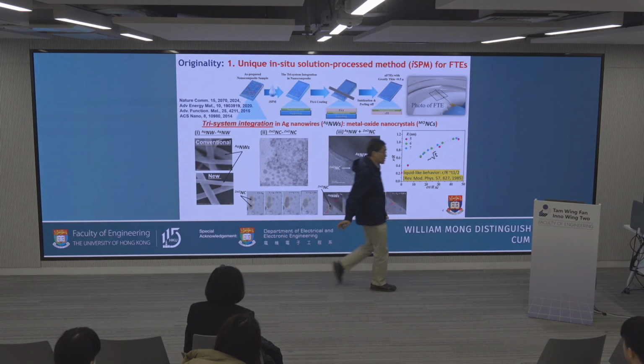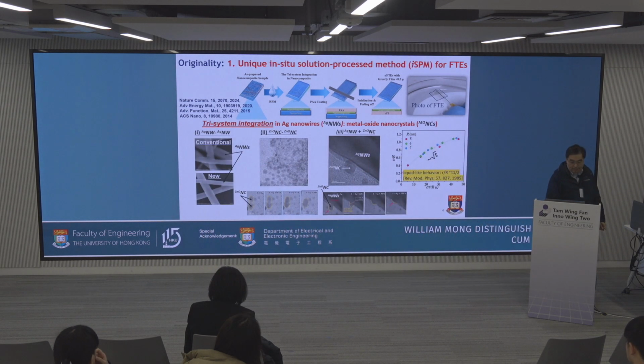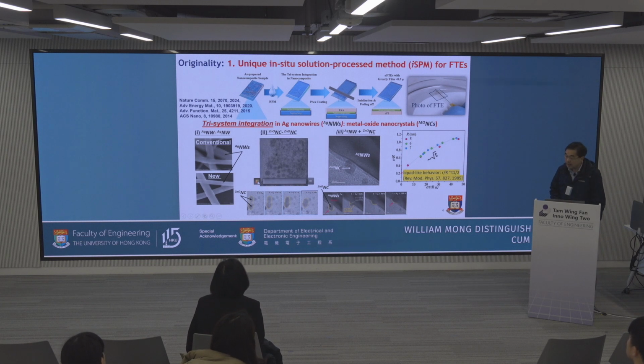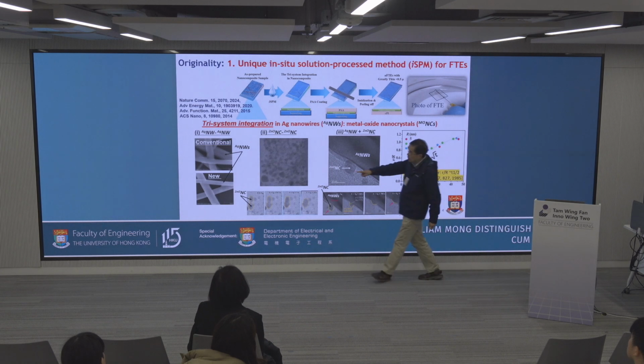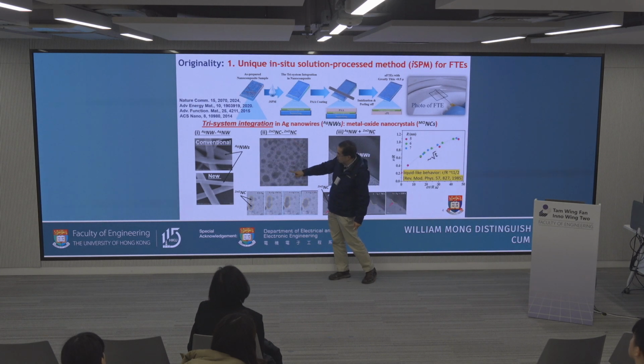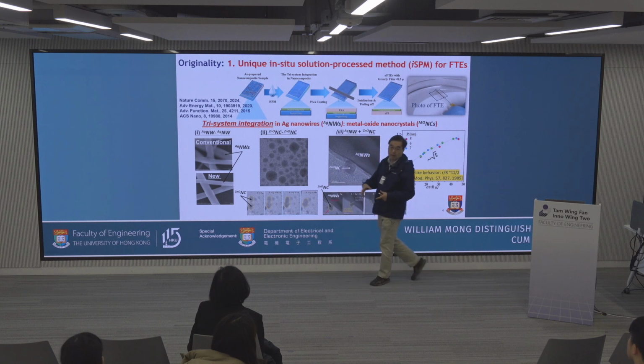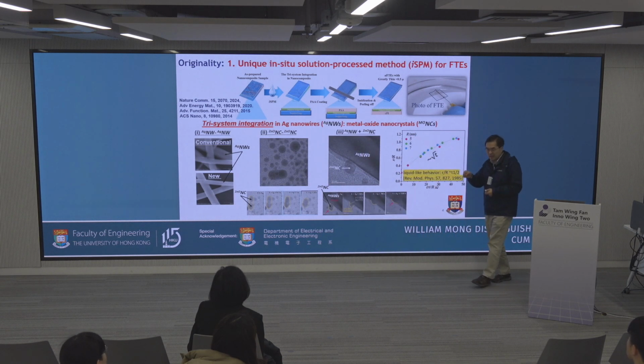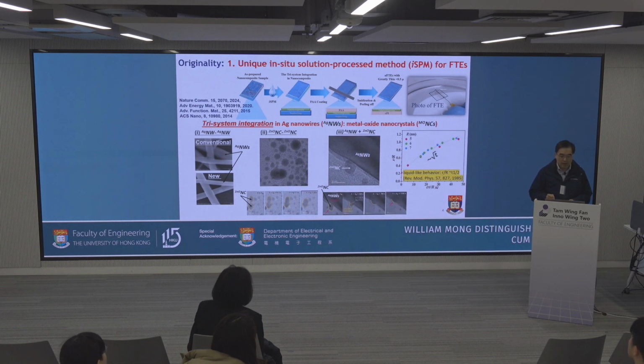Number two, the oxide itself, at the same time during the synthesis, is the second integration between the nanocrystals. The nanocrystals of zinc oxide, in this example case, will coalesce themselves, making a cluster instead of small, tiny nanocrystals. So this is the second integration happening during our process.